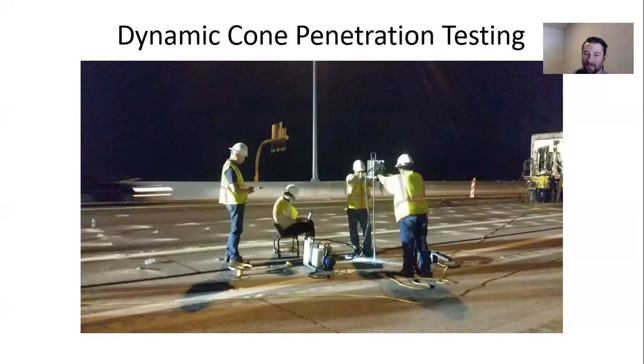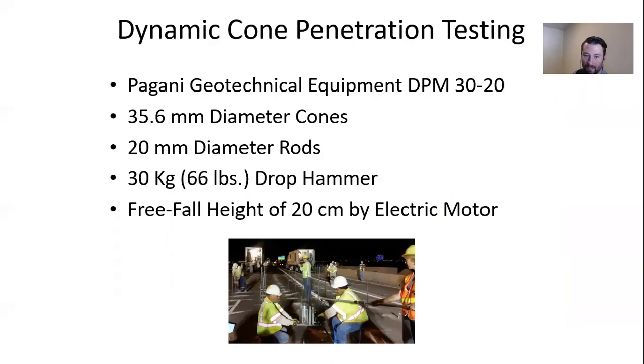That's Keith, his handsome self, there observing the penetration testing with the crew. The dynamic cone penetrometer, that's the device being held by the two men standing there. And similar to other forms of penetration testing, we're measuring blow counts. And in this case, we use a Pagani, so that utilizes 35.6 millimeter diameter cones. On top of that sacrificial cone is placed a 20 millimeter diameter rod, and a hammer, about 66 pounds, is dropped on top of that repeatedly from a free fall height of 20 centimeters.